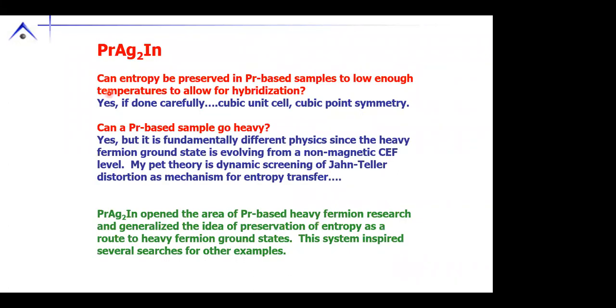So can entropy be preserved in a praseodymium-based system to low enough temperatures to allow for hybridization? Yes, if you do it carefully. Cubic unit cell, cubic point symmetry, right CEF splitting. Can a praseodymium system go heavy? Yes, but I think it's fundamentally different physics because this is a non-magnetic doublet, okay? And there have been beautiful measurements by Doug McLaughlin and others really confirming it's non-magnetic. So what we have here is instead of a dynamic screening of a local moment for a Kondo or heavy fermion, I think what we're having is a dynamic screening of a desire to have a Jahn-Teller distortion, which is indeed what happens in praseodymium lead-3, which has a similar CEF ground state, but it has a cooperative Jahn-Teller at low temperature that removes all the entropy. So praseodymium silver 2 indium then opened the area of praseodymium-based heavy fermion research and also generalized this idea of preserved entropy as a route to heavy fermion physics.